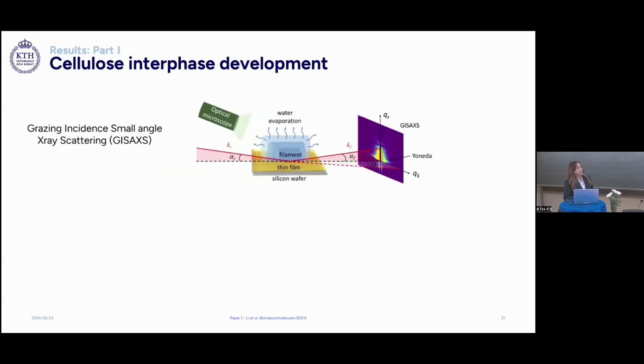In paper 1, the grazing incidence small angle X-ray scattering technique was used to study the development of the cellulose interface during drying. For this, a cellulose filament and a cellulose thin film were prepared and used as model materials. The filament was used in this case to create a larger contact area with the film and was prepared in a similar way as the beads.